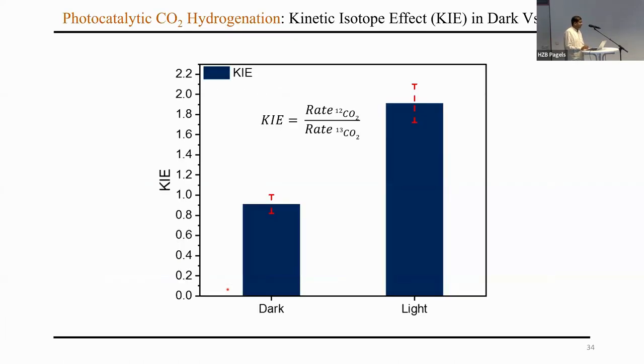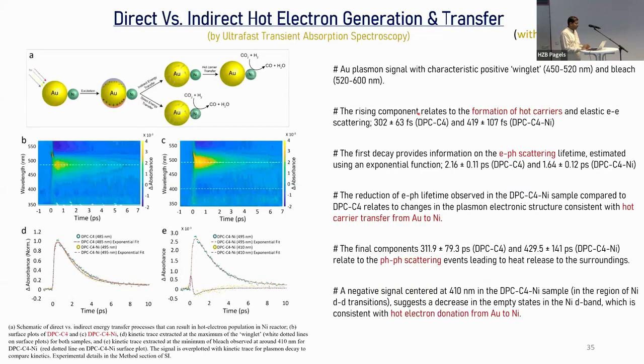We also carried out the kinetic isotope effect. And there is a theory which says that if the reactions are happening in the excited vibrational potential, if the reactions are going in the excited state, you will have a higher KIE as compared to when you are in the ground state. And that's what we clearly see. In dark, it's nearly one, but in light, it's around 1.8, which indicates again that it's an electron mediated reaction and not a thermal reaction.